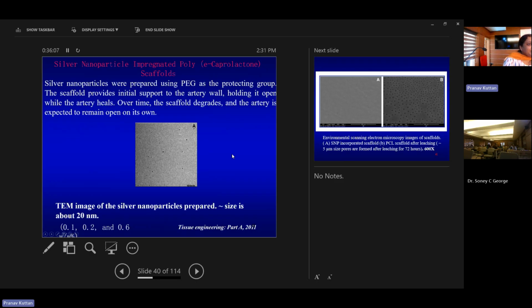So that is the idea, and it will also give pores. Once this PEG comes out from the membrane, the vascular scaffold will become porous, with small pores where the PEG has come out. And that porosity is very important for the regeneration of the actual vascular tissue, because natural materials grow only in such porous structures. That is how it is.